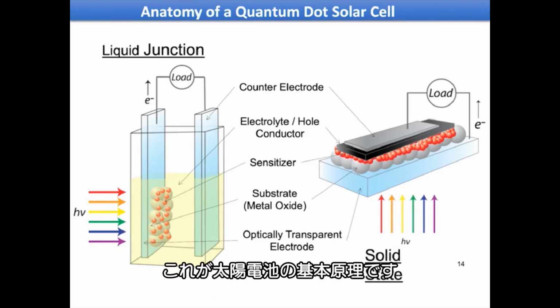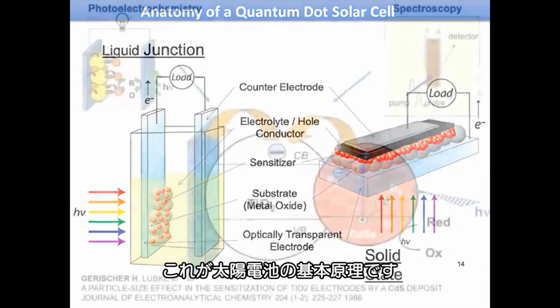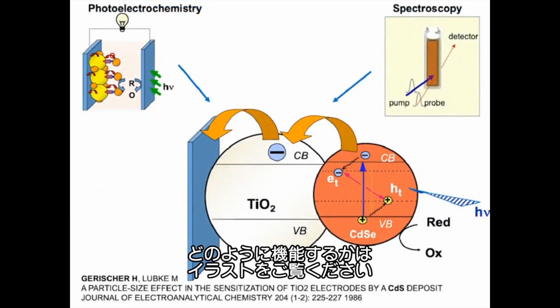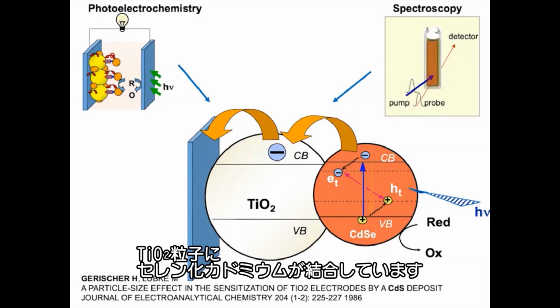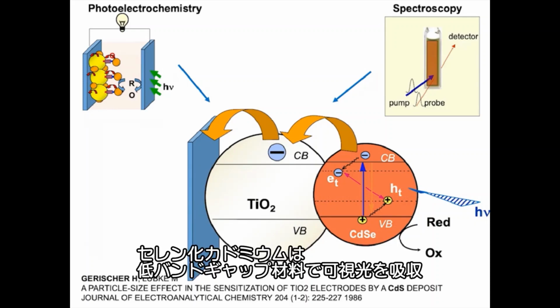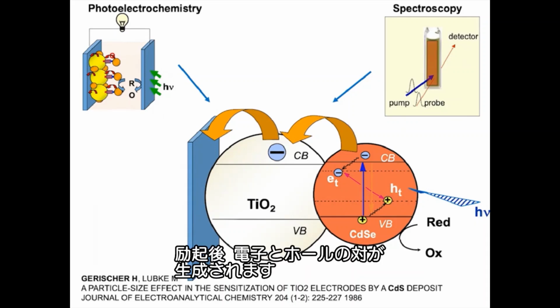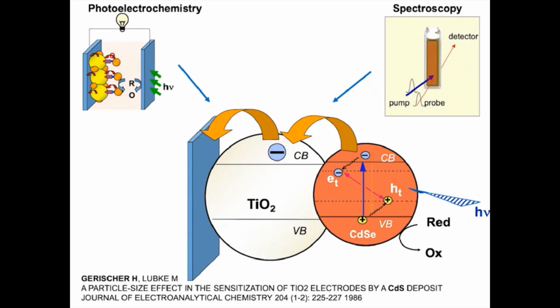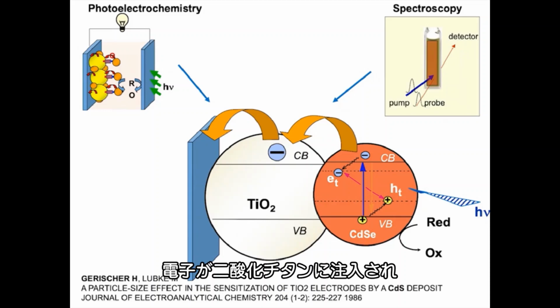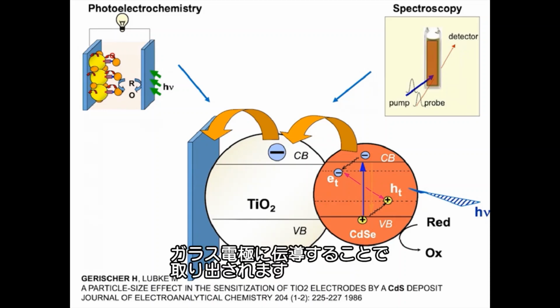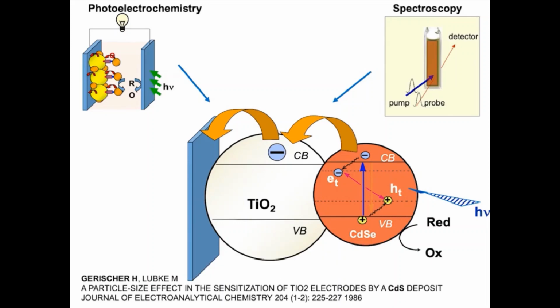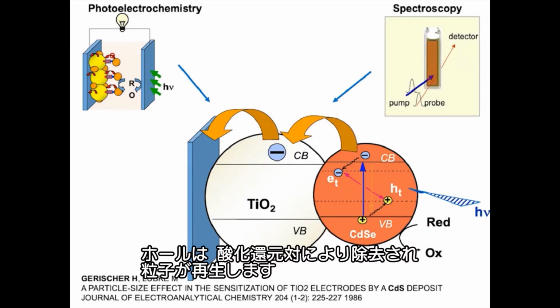So this is the basic principle of the solar cell, and the way it operates, you can see here in this cartoon. We have a TiO2 particle to which cadmium selenide is attached. The cadmium selenide is a low band gap material and absorbs visible light. Upon excitation you generate electron and hole pairs. The electrons get injected into titanium dioxide, which is extracted by a conducting glass electrode. The holes are scavenged by the redox couple, and this way the particle is regenerated.